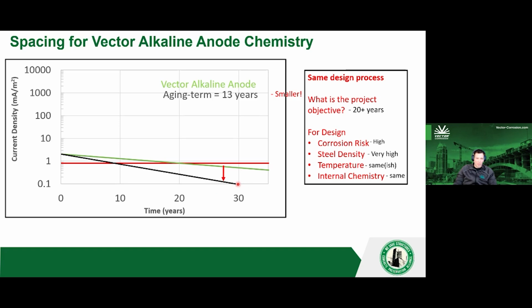And the slope, as a result, is much, much steeper, and you're getting a much shorter life than you want to have. So it would be difficult to fit a proportional amount of zinc into the structure and still achieve that life extension goal, just because of the amount of steel. We need to fit a proportional amount of zinc. Really, really tough to do in this case. So what else could they do?